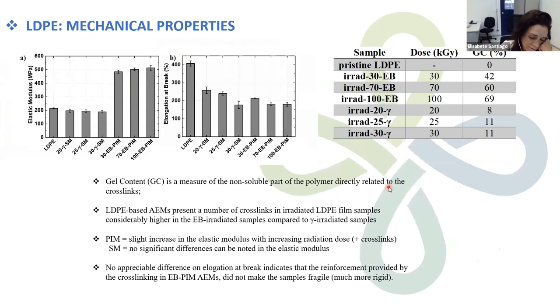We studied the influence of the method on the mechanical properties. Tensile tests have shown that the AEMs obtained by pre-irradiation have a higher elastic modulus. This indicated that the samples become more rigid by pre-irradiation, by submitting them to EB. This feature is probably associated with the presence of a large number of crosslinks, which was proved by gel content measurements. Okay.